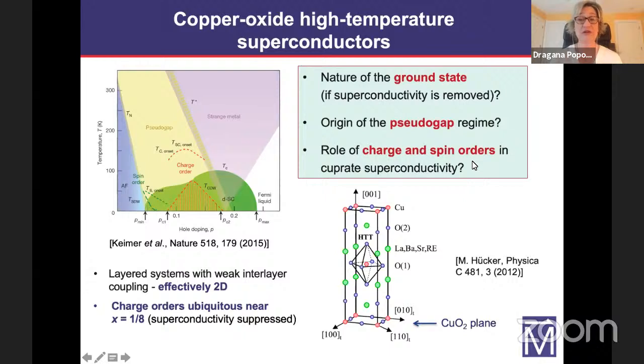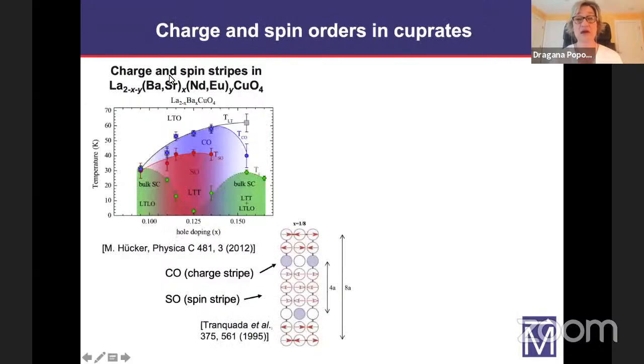For example, spin orders have been known from very early on. In some materials, like the lanthanum 214 family, they coexist with charge orders. In particular, in these materials from that family, they are strongly intertwined. In each copper-oxygen plane, charge and spin orders appear in the form of stripes. So here is a sketch of one plane. So charge stripes are separated by hole-poor antiferromagnetically ordered spin stripes. So the stripe correlations are strongest at 1/8 doping, where Tc is very suppressed, as you can see here, to very low values of only a few Kelvin.